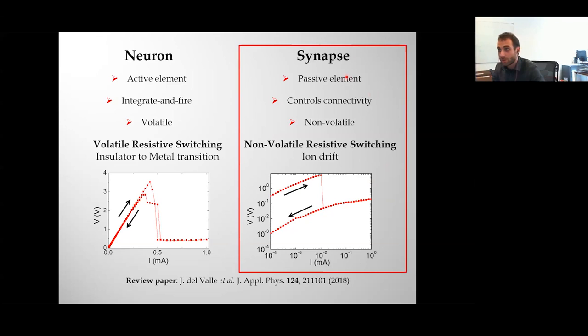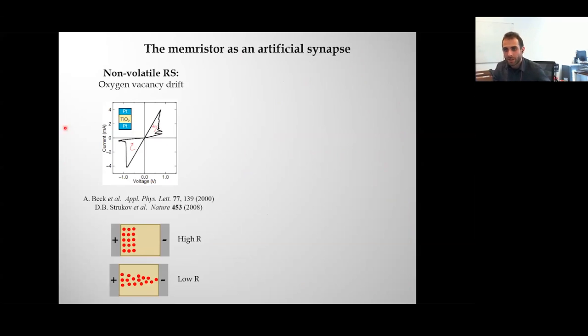So I'm going to focus now on this part, which is what has been worked on the most over the past decade, which is how to use this non-volatile resistive switching to emulate how a synapse works. So that's the memristor as an artificial synapse. Here you have a typical IV of non-volatile resistive switching. You have this butterfly cycle in which you have two branches, a high resistance and a low resistance branch, and you can change from one to the other.